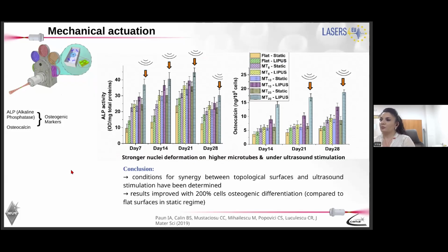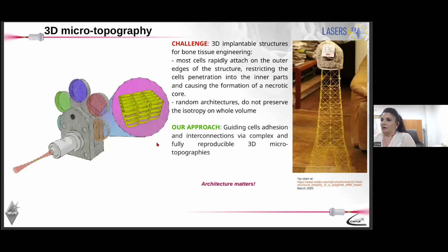We checked if this effect of changing the shape of the cell nuclei is positive for our final goal, which was to improve the osteogenesis. For this, we checked two osteogenic markers, alkaline phosphatase and osteocalcin. Both of them showed that the best result was obtained here, in yellow marks, for the highest microtubes subjected to mechanical stimulation, which I recall corresponds to the highest deformation of the cellular nuclei. Well, we went a little bit further.